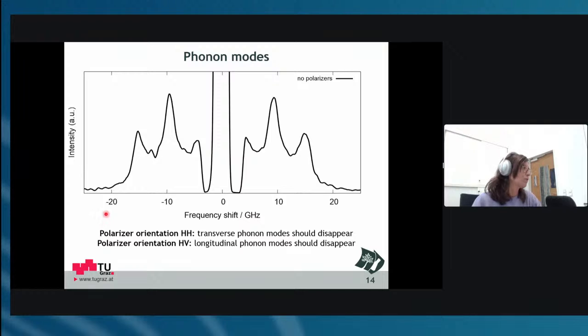So when I just do a measurement, this is a spectrum of a fiber material, you see the intensity again and the frequency shift. And when I measure this material with no polarizers in my light path, then I will get these two peaks. This is noise. This you can forget about.